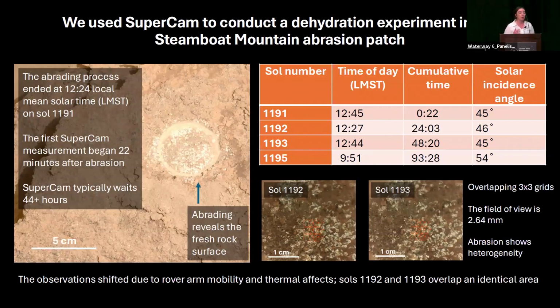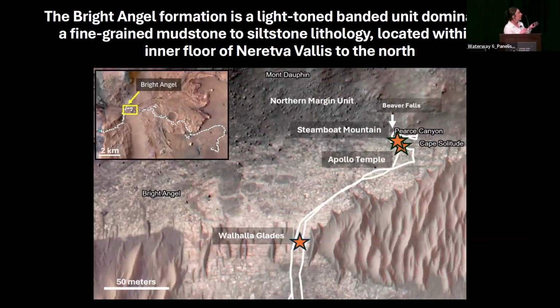So SuperCam typically waits about 44 plus hours before characterizing minerals in abrasion patches. But we know phyllosilicates and other minerals can begin to lose adsorbed water within 24 hours. So what we did was we arranged the plans within the rover, and we did our very first measurement 22 minutes after abrasion instead of 44 hours. And we did that on the Steamboat Mountain abrasion patch. One extra thing just to note is that it's very important to indicate the times of the abrasions, because that can also influence the 1.9 micron band.